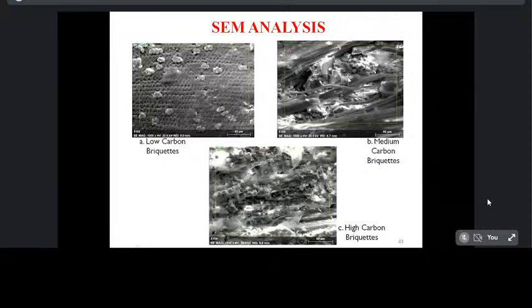The briquettes are characterized by the deposition of carbon in large and small spherical particles. The high carbon sample image shows longitudinal cracks, but the formation of ridges is not witnessed. In the sample with larger lumps, carbon particles are distributed overall equally, and the substances with ridges in all the samples are the fibers of the sorghum panicle and pearl millet. So the high carbon briquettes have good quality in the image.